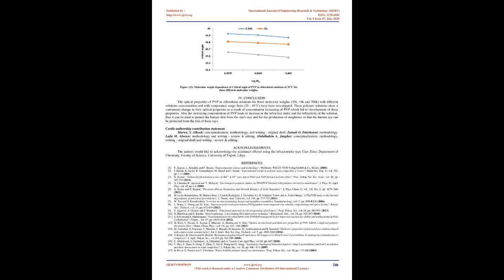The critical angle's dependence on the molecular weight of the PVP in chloroform solution, for 3 selected concentrations, 0.3, 1.0, and 5.0%, and a selected temperature of 35°C, as an example, is shown in figure 9. It has been seen that increasing molecular weight shows a rather rapid increase in the critical angle of the solution. This general increase of the critical angle with molecular weight may be due to the increase of polar side groups in the molecular chain of this polymer.